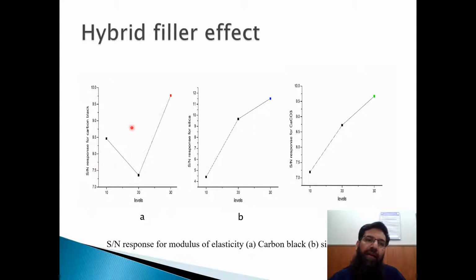There's a lesser change in the moduli as we add the carbon black, and there's a more change in the moduli as we incorporate the calcium carbonate. But the maximum change in the moduli will be got when we incorporate the silica as the nanofiller. So out of all these three fillers, if we compare, the silica would give us the better increase in the moduli as compared to the carbon black and the calcium carbonate. If we compare these three fillers in the automotive application, the silica would be the better option as compared to the carbon black and the calcium carbonate.